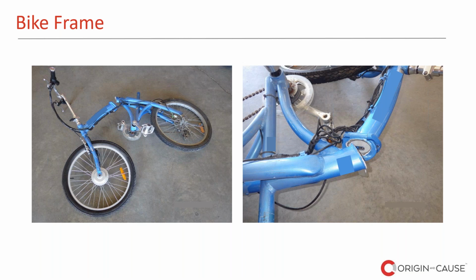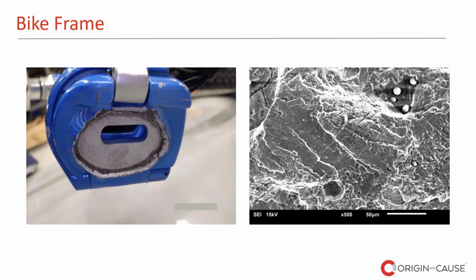In order to examine a fracture surface, oftentimes you have to cut that evidence in smaller pieces for easy handling in order to fit under the microscopes. So in this particular case, like in the tie rod before, we cut the section containing the weld and we took it for examination in the lab. On the left side the image, you will see the overall view of the fractured weld. And on the right side image, again, our friend, the scanning electron microscope, provided significant evidence to show that the failure was the result of fatigue. The features that indicated fatigue are so-called striations, and there's parallel lines which are indicating the fracture progression.